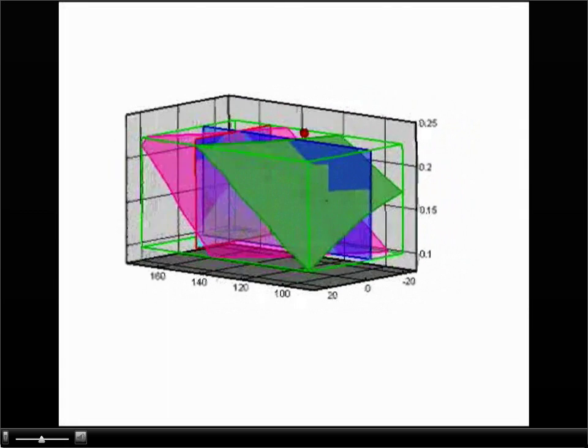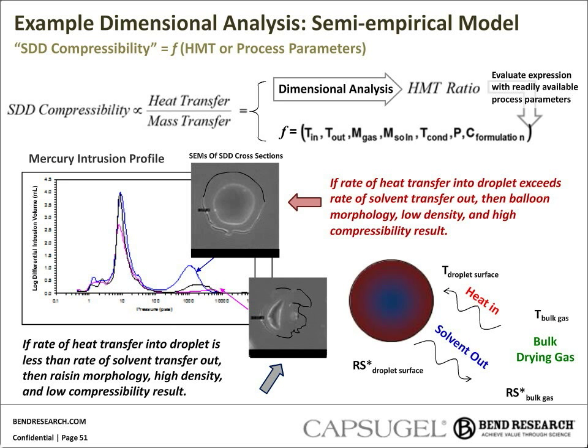So earlier we showed that SDD density or compressibility often correlates well with outlet temperature. The added condenser temperature parameter, and to better account for scale, we developed a dimensionless parameter that takes into account all of the key thermodynamic process parameters. A dimensional analysis was performed on an equation for the rate of heat transfer into the droplet and the rate of mass transfer out of the droplet. And that resulting dimensionless parameter was evaluated using the easily measured and available thermodynamic process parameters like temperatures and flows, and correlated to the SDD compressibility as measured by mercury intrusion.